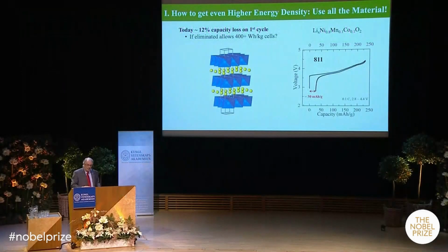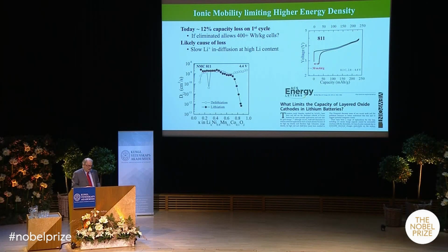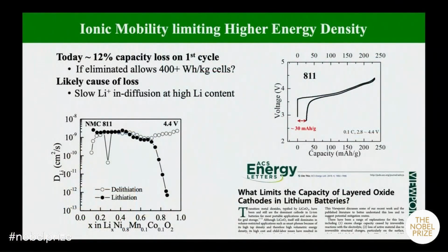So we've been doing some basic research there, and what we find out is it's the fundamental behavior of these materials, really how fast do these lithium ions move or how fast they don't move. So you can see here, don't worry about the numbers here. This is how fast they move. Then once you get to about 80% lithium in there, this drops off by 4 orders of magnitude. So a huge drop off in the diffusion coefficient.